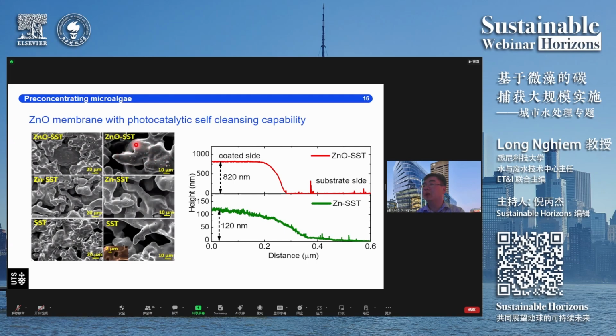And when we coat the membrane with zinc oxide, you see that the membrane pore size doesn't change because our coating layer is very thin. And indeed, you can see here that for zinc oxide coating, we have a layer of about 820 nanometer. And when we first coat zinc metal and then oxidize into zinc oxide, we have a layer of about 120 nanometers. So it's very, very thin and small compared to the pore size of the membrane.